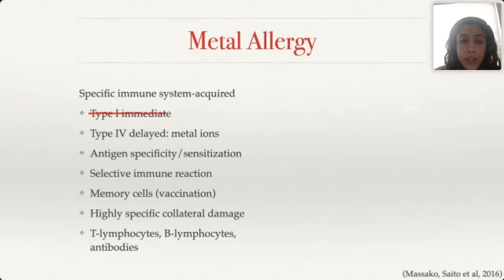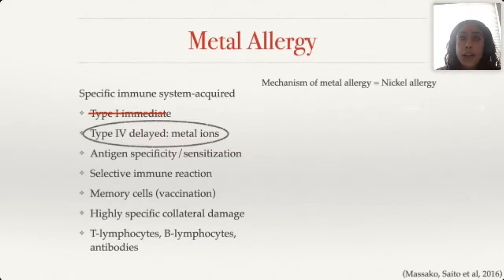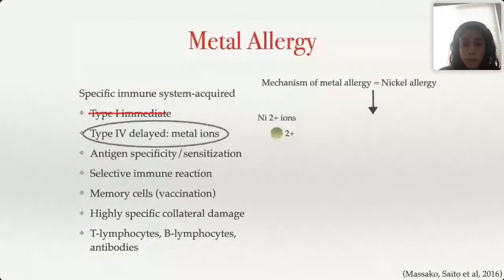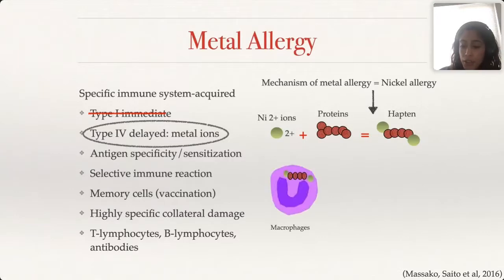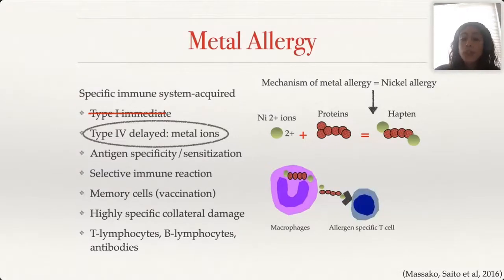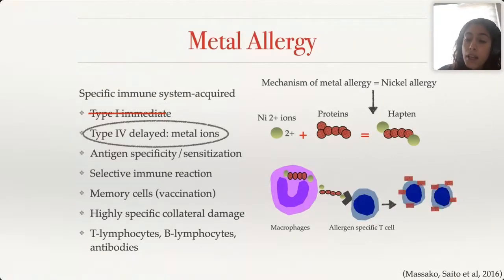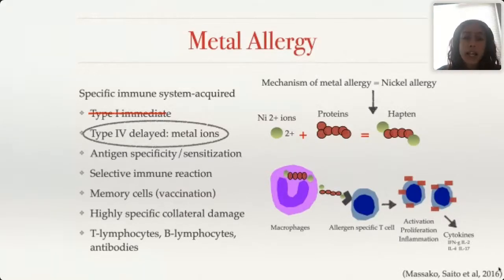A little bit about metal allergy. Allergy occurs either through type 1 or type 4 of the specific immune system, but with metal allergy it's type 4, and it really happens only to the alloy particles of the titanium implant, not to titanium itself. The alloy of the titanium implant usually contains nickel, cobalt, and chromium, so if it happens, it's mostly to nickel. Nickel ions activate and form haptens, essentially antigens. These antigens are presented by antigen presenting cells to T cells, which get activated and proliferate, starting the cycle of inflammation through activation of cytokines, interferons, and interleukins.